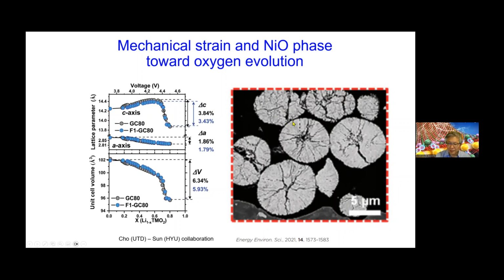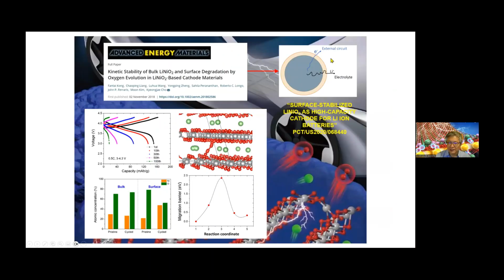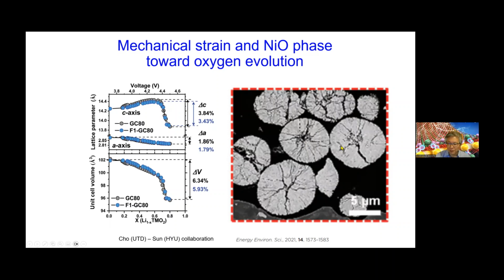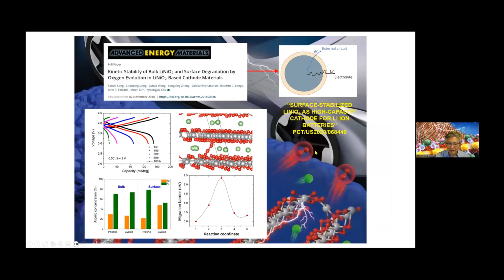Well, the point is that even if we do this type of coating to stabilize, the particle is breaking, exposing new surface, which will be prone to have the same oxygen evolution problem. So the root source of the problem is actual volume change. This is the reason why, when we use a lithium-ion battery in our cell phone, over time the capacity is going down, because the cathode material over hundreds of cycles is going through this fracture and exposure to liquid electrolyte and degradation, losing the capacity, to a lesser degree, but qualitatively the same mechanism.